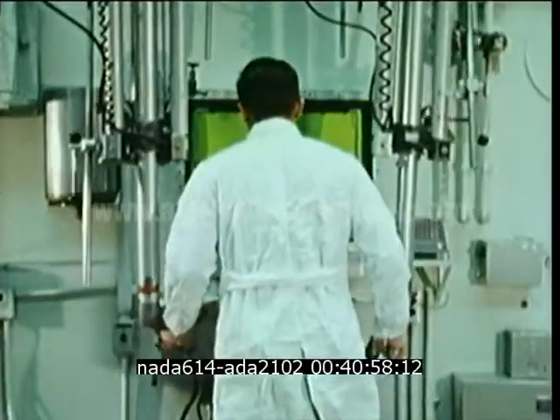Despite the high rate of fuel melting, cladding rupture, and the spewing of melted fuel, the immediate transfer of heat to the water left the adjacent aluminum cobalt flux wires unmelted. The remaining boron strips were gray in color, obviously brittle, and easily broken by hand manipulators.